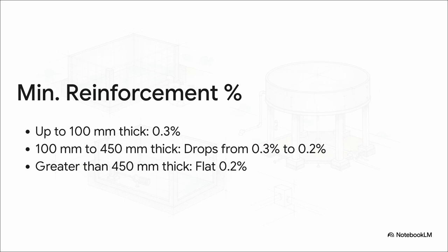To fight back against shrinkage and temperature variations, we need minimum reinforcement, and it actually operates on a sliding scale. Think of it like this. For thin members up to 100 millimeters thick, you need 0.3% of the concrete area. As that thickness grows from 100 up to 450 millimeters, the requirement drops linearly down to 0.2%. And for anything massive, talking over 450 millimeters thick, it just stays flat at 0.2%.